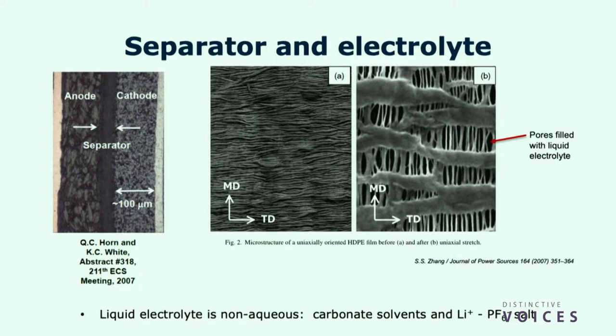This is a polymer layer, about 25 microns thick. It's like paper. It's porous. And filling those pores in the separator is a liquid electrolyte. It consists of a non-aqueous solvent, can't have any water. Lithium batteries hate water. Carbonate solvents. And it uses lithium.